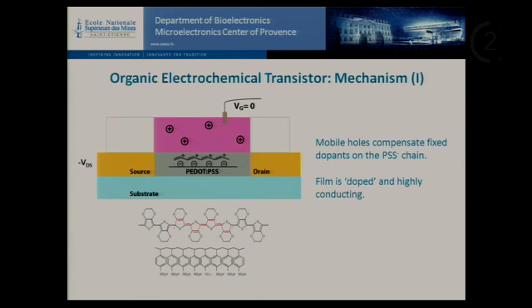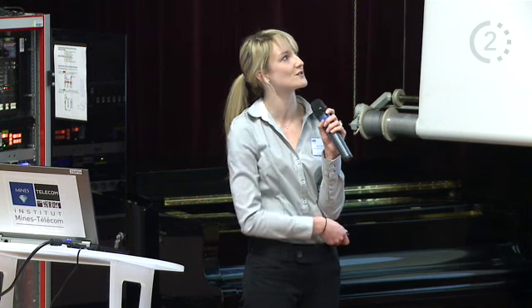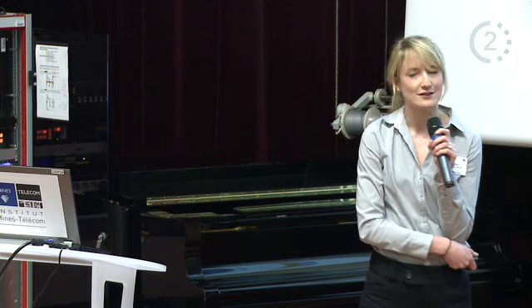The negative charges are compensated by positive holes along the PEDOT polymer chain. These positive holes are very mobile, and in the presence of the field or a voltage drop across the source and drain, they easily move. In this state, the film is considered doped and is highly conducting.